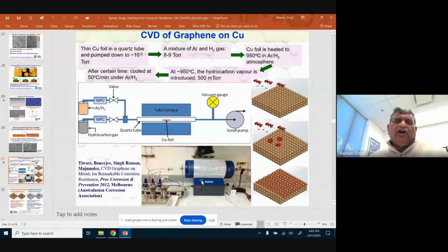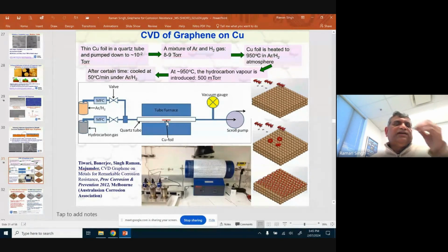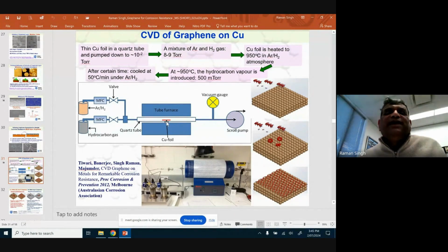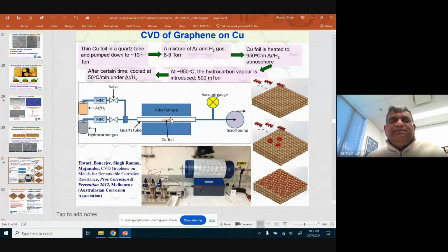Let me talk a bit about how we develop graphene on metal by CVD process. What we do is that we take a furnace, we place the metal on which we want to develop graphene, and we heat it to high temperature, and then we pass hydrogen. Why do we pass hydrogen? Because most engineering metals will have a native layer of oxide on the surface, like copper will have cupric oxide. We want a pristine copper surface. So you pass hydrogen, it reacts with Cu2O or CuO, and it transforms into Cu plus H2O, and water is pumped out, and you have pristine copper surface.